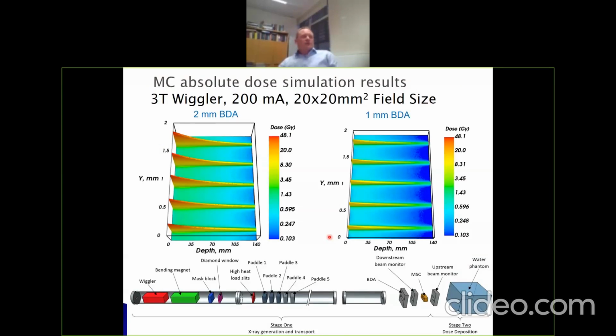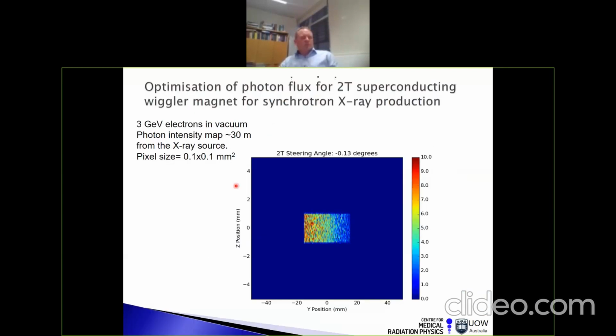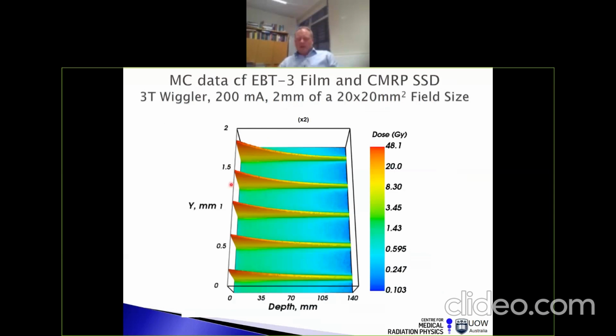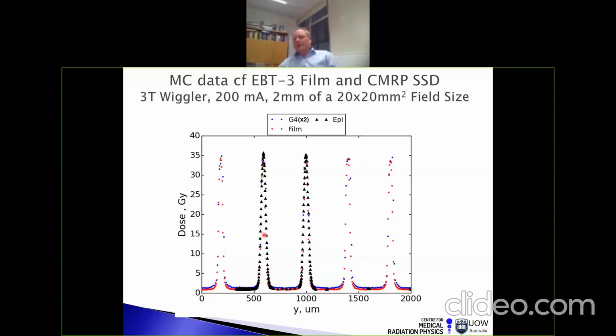And then we get these simulated microbeams. This is a 3D plot of the dose as a function of depth, going down to 140 millimetres, and these are the microbeams produced after the multi-slit collimator. Then we can zoom in on one of these, take a cross-section and compare that with experiments. That's what we've done, and you can see here the experimental data is fitting extremely well to the simulations. We've still got some work to do down in these regions, and that's ongoing at the moment. But this is some of the first time that this sort of work has ever been done, and this detector system is the first one that's ever been developed in the world as well.